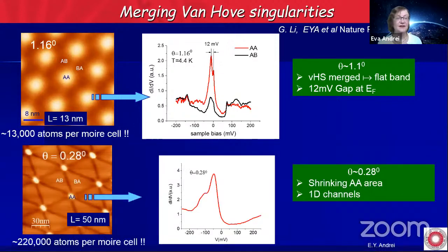And then as we continue to decrease the angle, now this is 0.28 degrees, now you see these AA regions, which are the bright regions, have shrunk as much as they can. They're down to less than 10% of the area of the Moiré unit cell because of this energetics. There's a lot of strain built into this. Of course, you can't get rid of the AA just because of topology. So these are kind of like vortices, and these are connected by lines, which are these saddle points. A lot of interesting things are happening there, but I will not discuss it here.